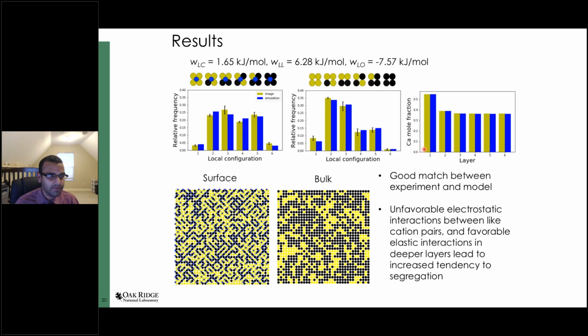So here we have the calculated, as a result of this optimization, the calculated interaction energies. And you can see, this is lanthanum calcium is 1.65 kilojoules per mole, so rather small. Lanthanum repulsion is quite large, as you would expect. And then the lanthanum oxygen interaction energy is negative, as you would expect as well. And so here is the comparison to experiment.